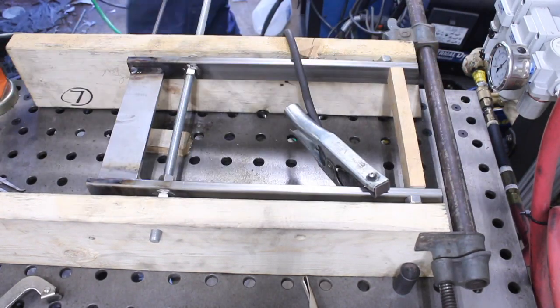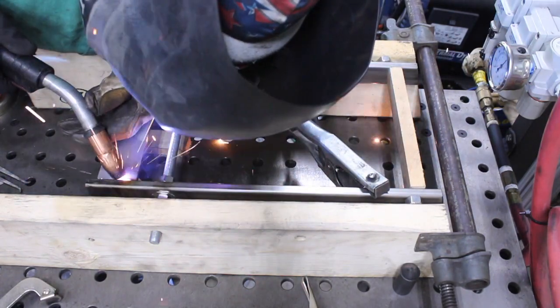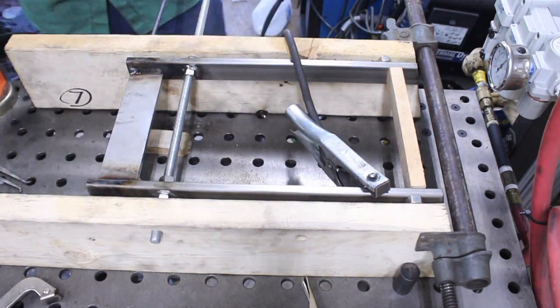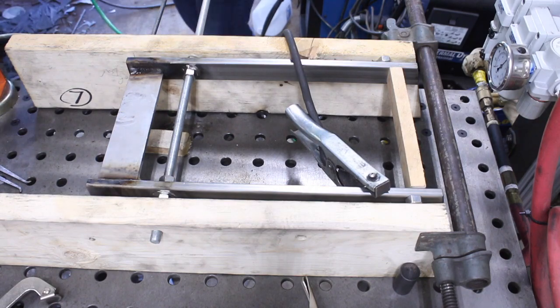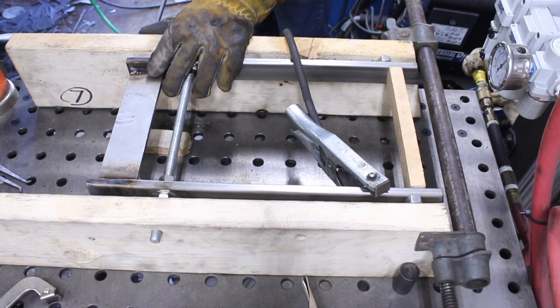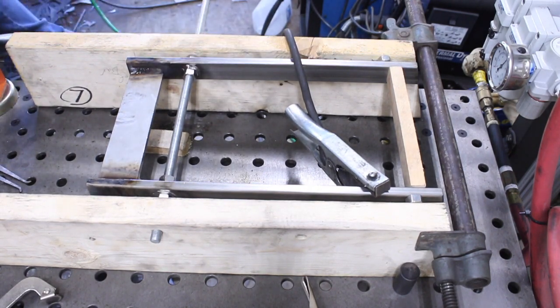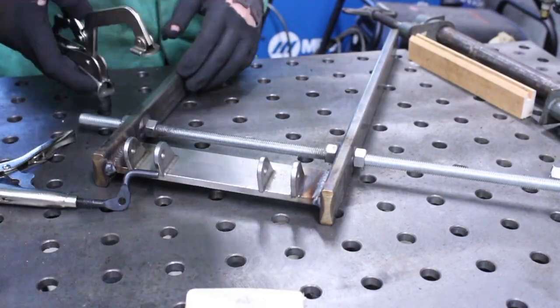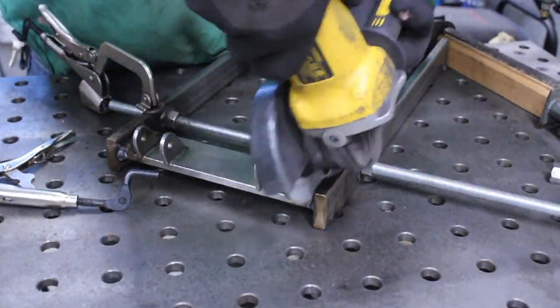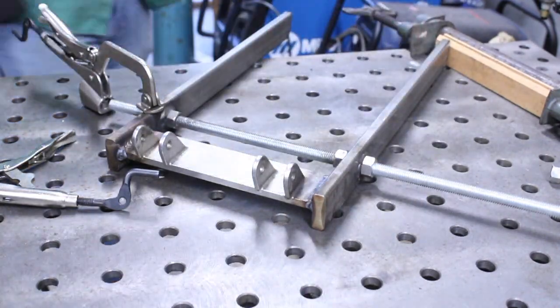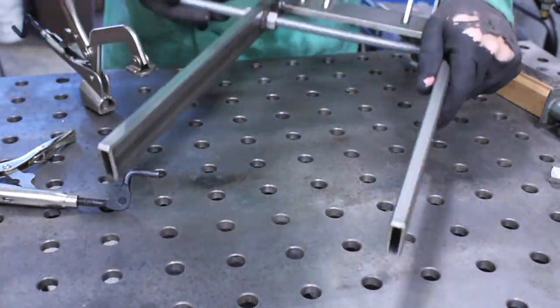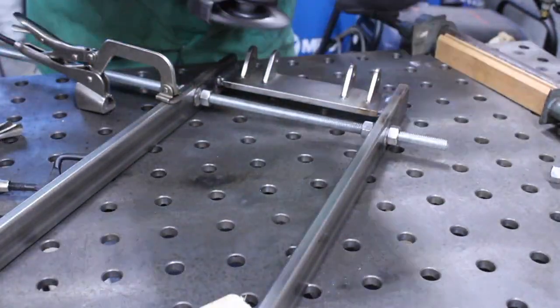And again, I can't stress this enough. Make sure any tools you use to prepare stainless are only used to clean stainless. For example, if you use a stainless steel brush to clean carbon steel, don't use it again on any stainless steel. This is also true for stainless hammers, picks, and clamps. Trace amounts of carbon steel can transfer to the stainless, causing it to rust.